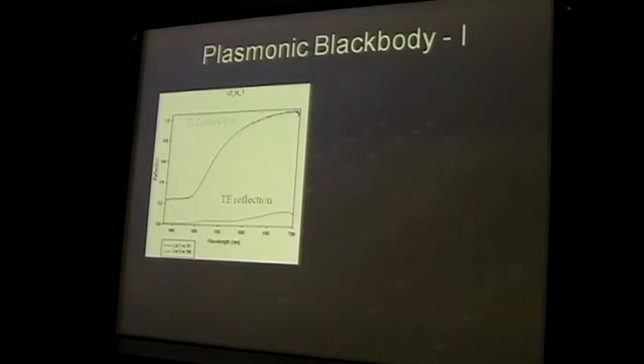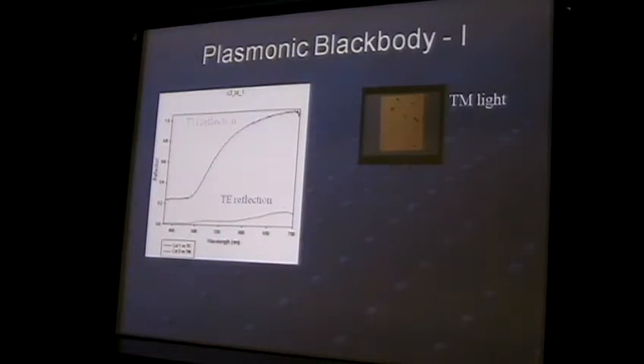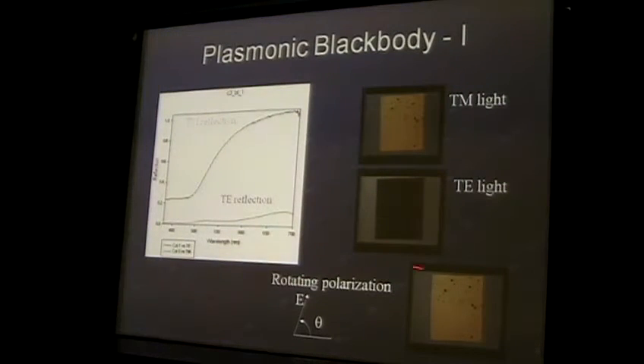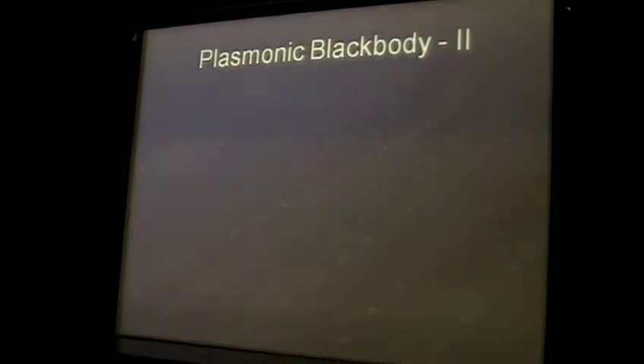If you look at the reflection in two different polarizations for this structure, you can see that for one polarization it behaves exactly like gold - that's the typical gold reflection. But for the other polarization, the reflection is pretty low - at the level of about 5% across the visible spectrum. The transmission of the structure is also zero because it's about 140 nm gold on average, which doesn't transmit light. The color of the structure changes when you rotate the polarization.